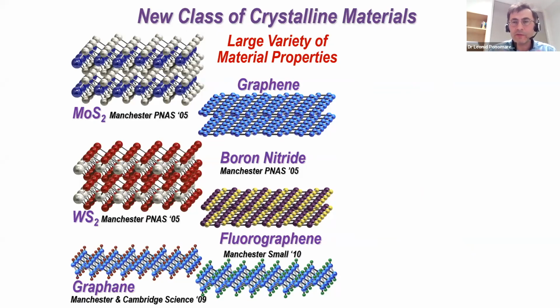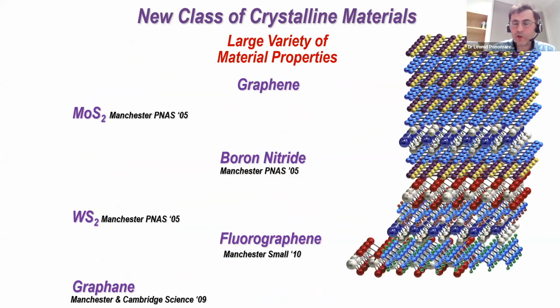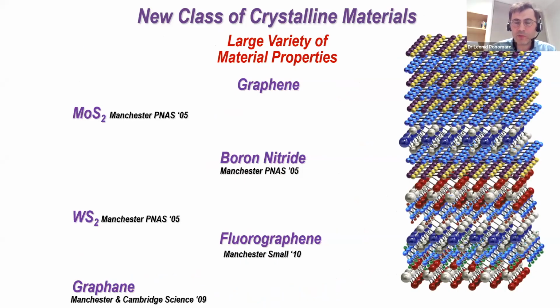What is even more interesting is that we can combine these materials together. We can place one material on top of another, making three-dimensional stacks. This is a new way of making artificial 3D materials with new, I would say engineered, properties, and this has been done. What is even more interesting is that it's not only the order which is important, but also the orientation. If there is a rotational misalignment between two different layers, the properties of such a stack change again. This is a very hot topic at the moment in graphene research and in research on two-dimensional materials.